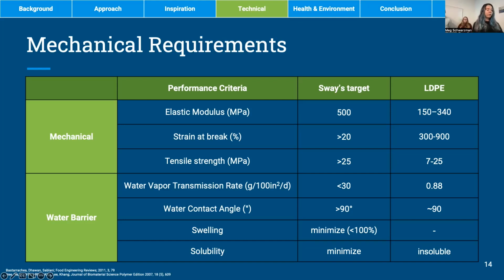It's worth noting that we back calculated this number from all of our various studies, as it is film specific and related to the broader category of water vapor permeability. And we converted everything to the units of grams per 100 inches squared here, since those were the units that SWAY provided to us for our target, and we wanted it to map on as easily as possible. The water contact angle then is a measure of hydrophobicity. So generally speaking, a water contact angle greater than 90 degrees defines a hydrophobic surface.